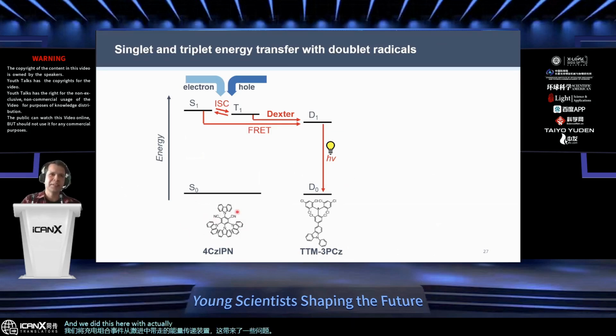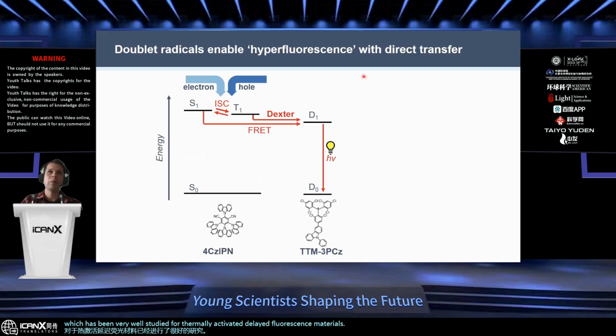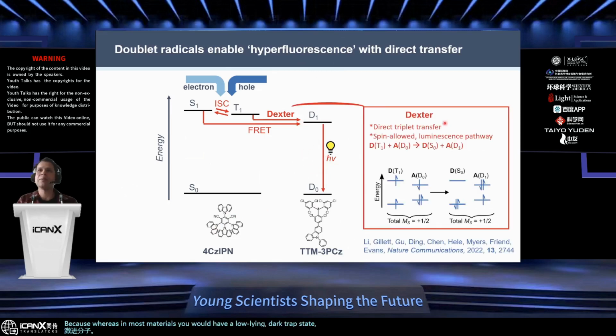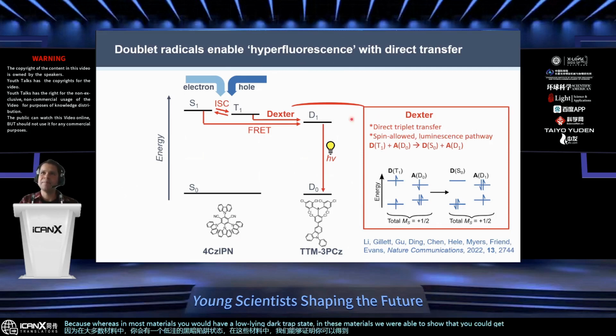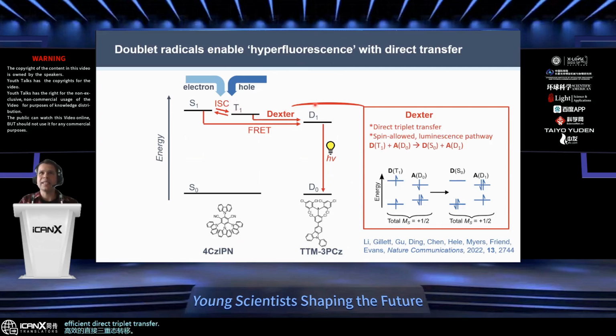And we did this here with actually a sort of fruit fly material for the organic emitter community, which is 4CZ-IPN, which has been very well studied for thermally activated delayed fluorescence materials. What we were able to do is to take this concept of a sensitizer that transfers to a terminal emitter that is used in the TADF community and actually show some benefits of doing that with radicals. Because whereas in most materials you would have a low-lying dark trap state, in these materials we were able to show that you could get efficient direct triplet transfer from this triplet state to this luminescent radical state.